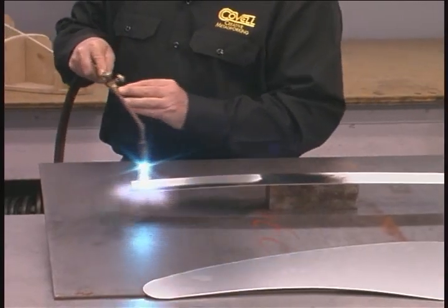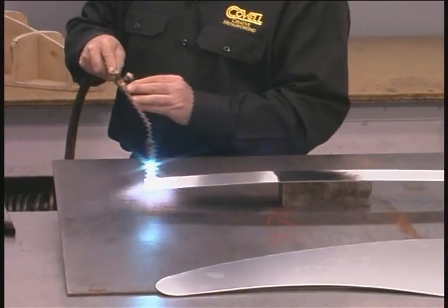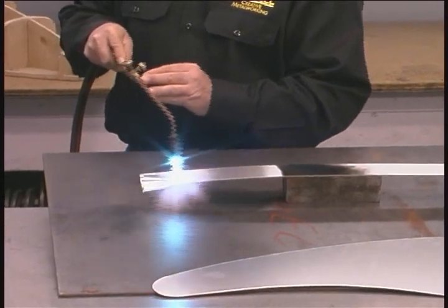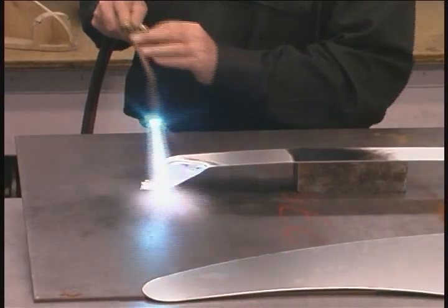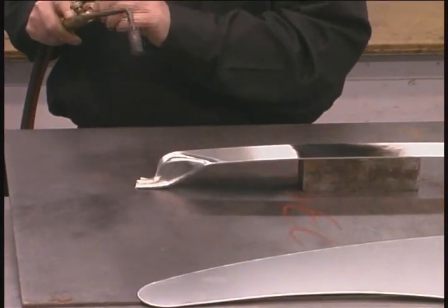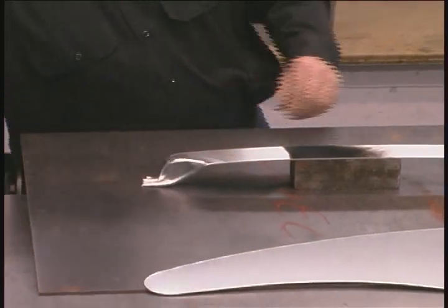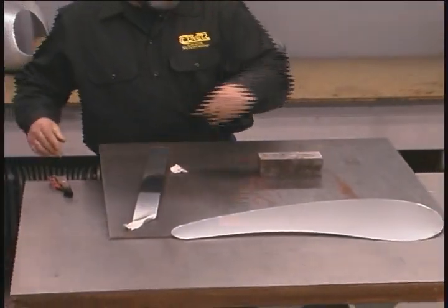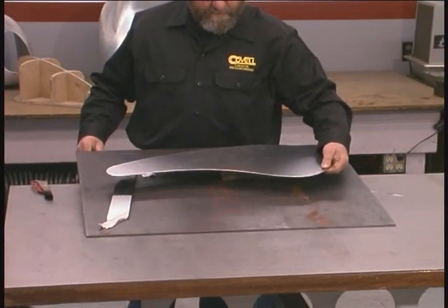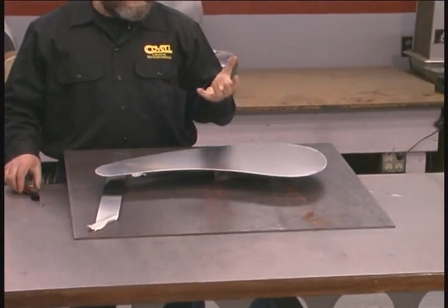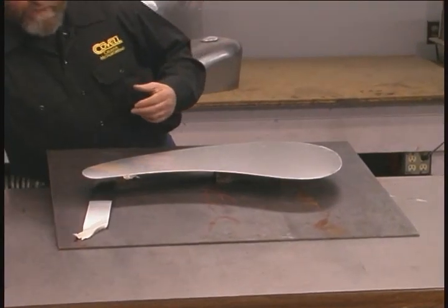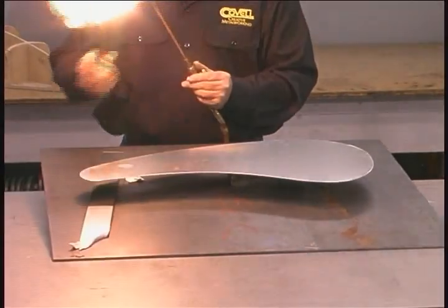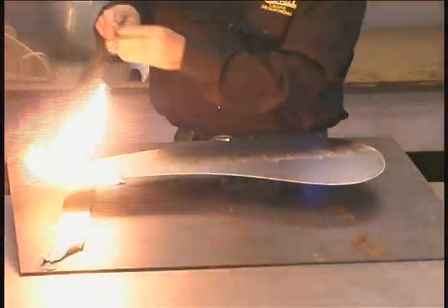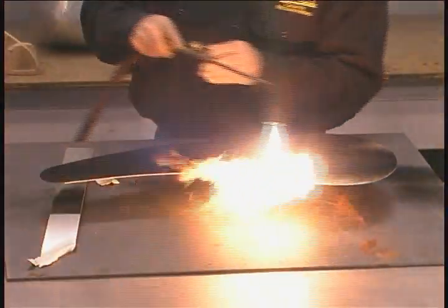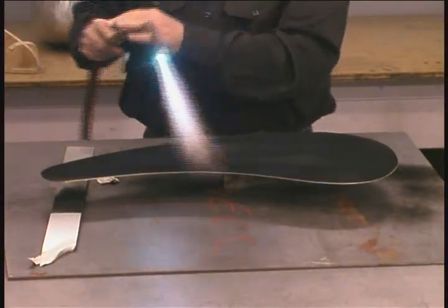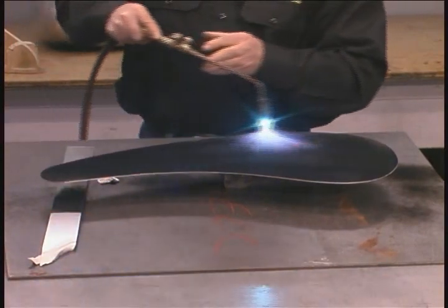So the soot film will burn off at just about 800 degrees, but it's very important that you don't overheat the metal, because we're just about at the point where it starts to melt. So be very certain not to overheat the metal. So let's get this molten piece out of the way. We'll get the gas tank half on the table. Spacing it up off the table helps keep the table from sucking heat out of the metal. And we'll put a soot coating on this piece of material. And then we'll heat the metal until the soot film burns off.